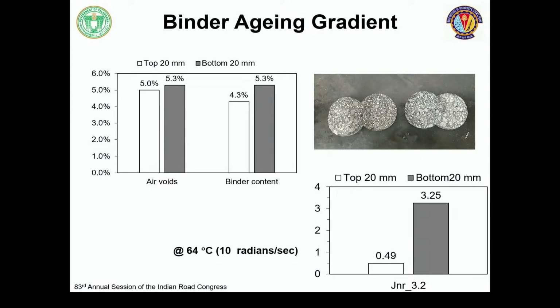Yeah, I think I mentioned this, but I was waiting for this picture to come up. We sliced into two parts. And we found the bottom layer had 5.3% bitumen, that is our initial binder content, but the surface had 5% and 4.3% bitumen, which showed that there was a reduction in the bitumen on the surface because of raveling. As I rightly said, I cannot conclude and say authentically, because some more data is required and we have to continue with this study. Unless otherwise proven, it remains only a perception. One data point is not sufficient to conclude.